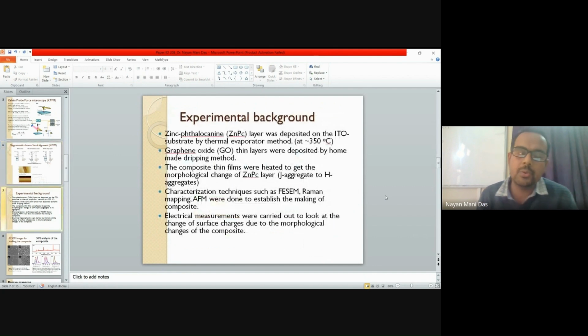So for the experimental background, I have deposited this metal phthalocyanine, which I used as zinc phthalocyanine, coated over an ITO substrate at around 350 degrees centigrade by the thermal evaporator method. Then graphene oxide material was deposited over the zinc phthalocyanine by a homemade dripping method. This composite thin film material was heated so that we can get the ZnPc, which has the structures of J aggregate and H aggregate. The heating basically changes the structures, which I will discuss during my results part.